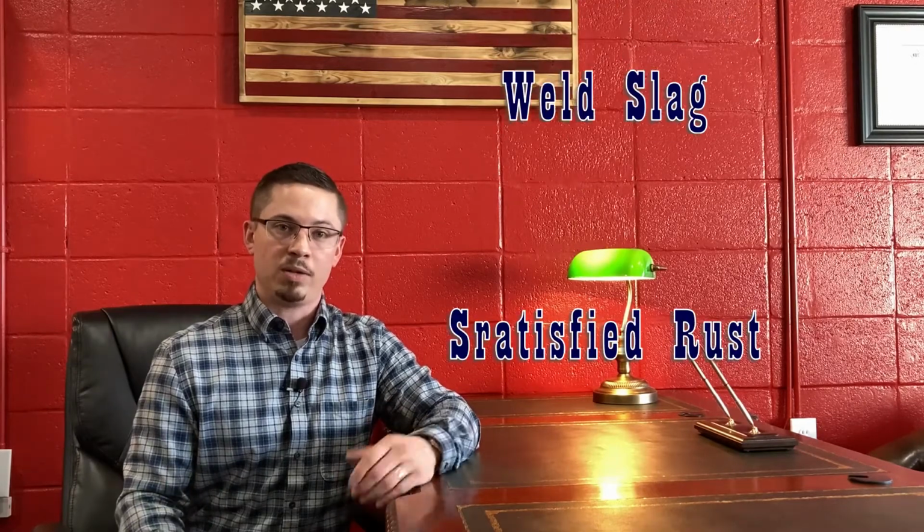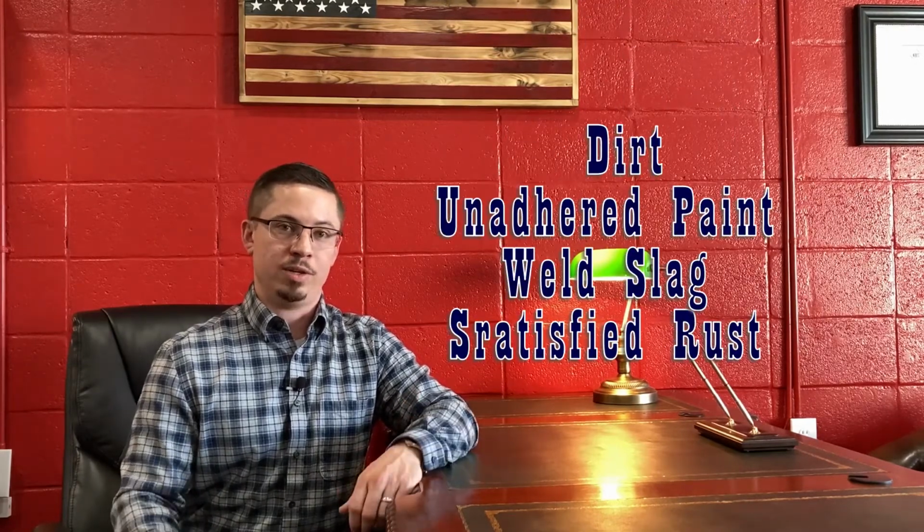Now, SP1 is solvent cleaning, SP2 is hand tool cleaning, and SP3 is power tool cleaning. And these codes or standards are not at all hard to follow, but I do bring them up together because both SP2 and SP3 require the initial performance of SP1, and most people tend to forget that. Now, to summarize these codes quite simply, they're only there to ensure the removal of loose foreign material, such as stratified rust, weld slag, loose paint, and dirt.